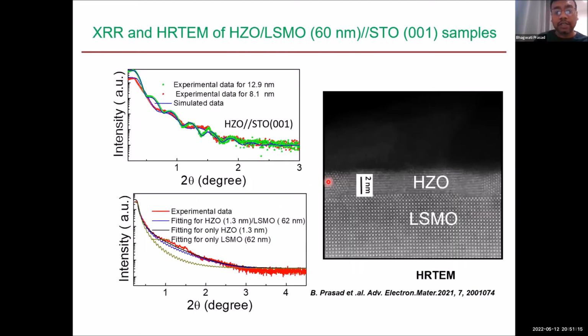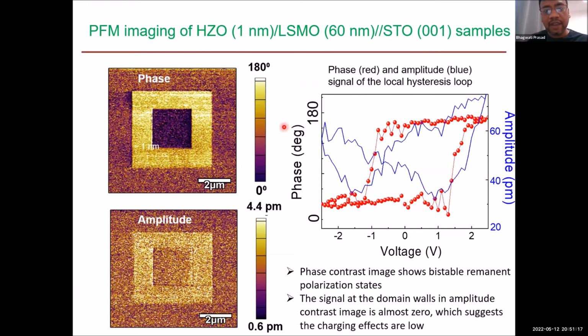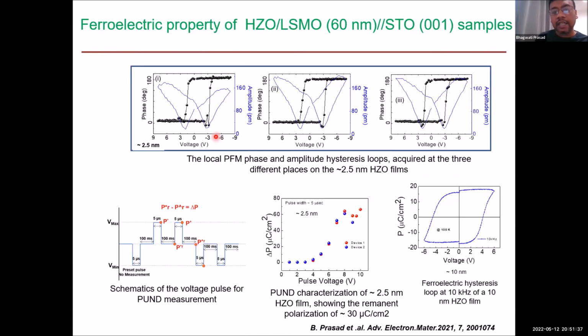With large in-plane strain, we could actually stabilize the ferroelectricity in the system all the way down to 1 nanometer. So this is the PFM imaging. What you see here is that the top one is the phase, and the bottom one is the amplitude. You can switch these 1 nanometer films one way or the other by applying the electric field. This demonstrates that you can switch them by 180 degrees, from one side to the other.